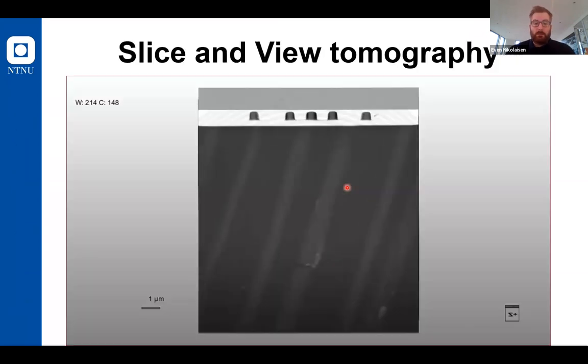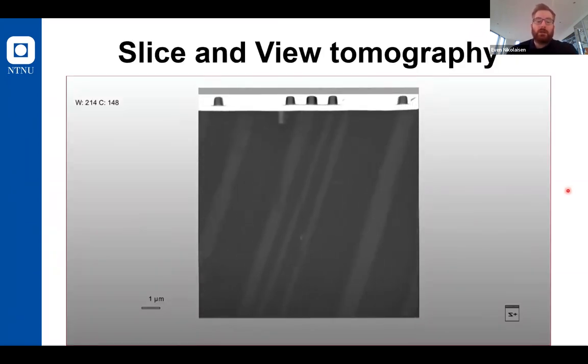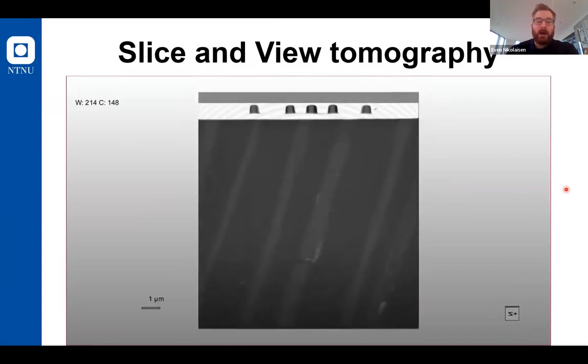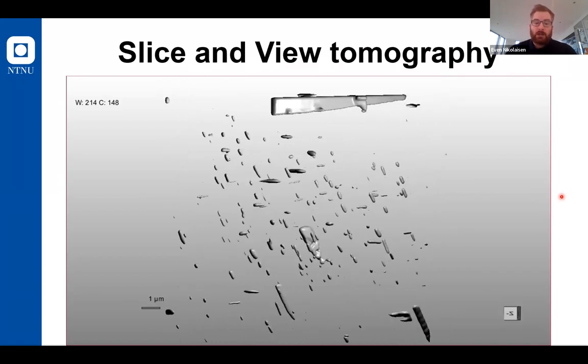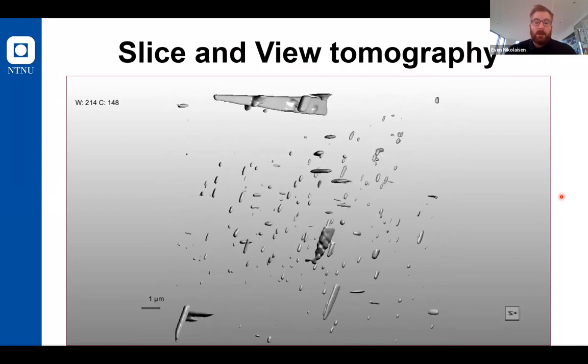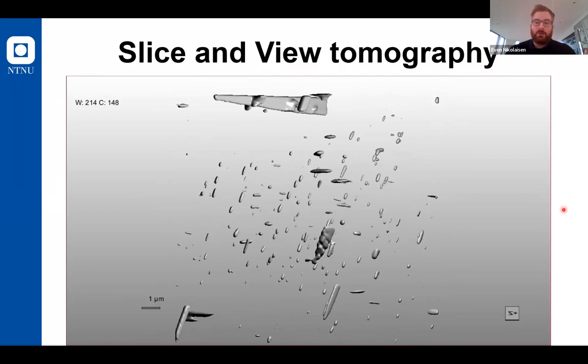Slice and view — for our purpose — is to actually slice with a focused ion beam SEM the micron-sized volumes of silicate. And then by removing the silicate, we can extract the actual individual magnetic particles inside. The advantage of this is that we can take the individual particles, apply 20 or multiple equidistributed field directions, and then calculate the magnetic hysteresis for each individual particle. Reassembling or summarizing all of the hysteresis parameters then generalizes a complete hysteresis of the overall volume.